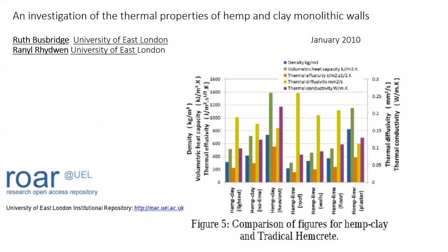This is another study from the UK, which suggests that you could lower the embodied carbon even further by using clay instead of lime. Lime is definitely the most energy intensive ingredient in the process, and clay can be used as a binder, or a binder with small amounts of lime has been demonstrated by a company called Cannabric in Spain. And New Mexico, for instance, permits building with clay. I think it is the only state in the US that has done that.